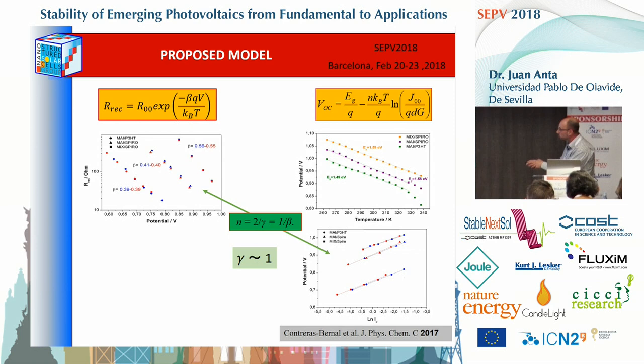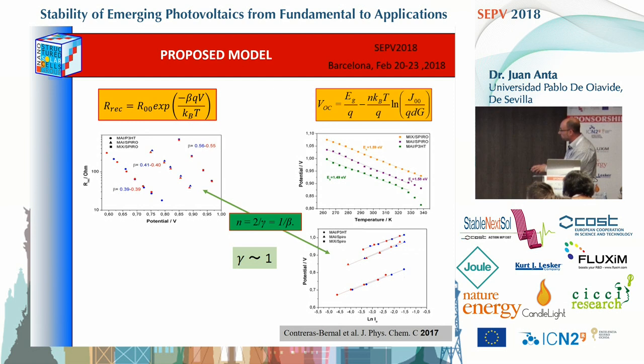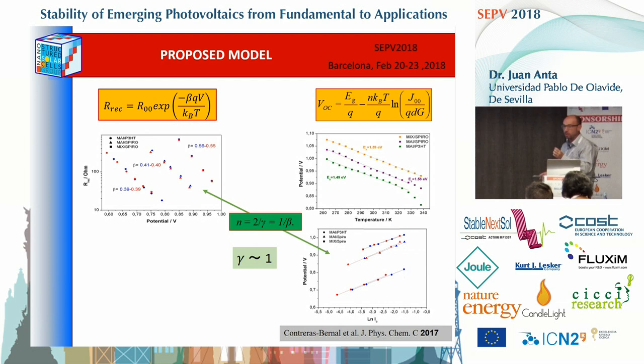All the recombination resistance versus voltage data fit to this expression, giving straight lines in a semi-logarithmic plot. When you plot open-circuit potential versus temperature you obtain a straight line, and extrapolating to zero temperature reproduces the band gap. Plotting potential versus logarithm of light intensity also gives a straight line. All data can be fit with exactly the same parameter: a gamma exponent of 1, corresponding to an ideality factor of approximately 2, meaning recombination is in the bulk via a trap-limited Shockley-Read-Hall mechanism.